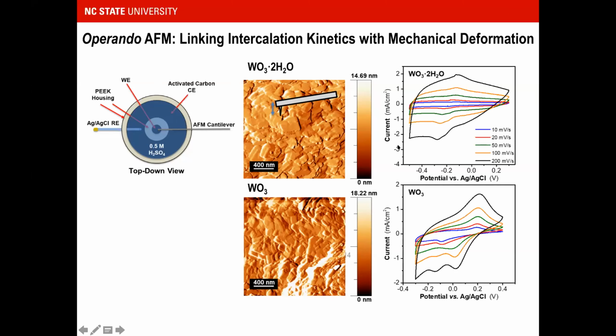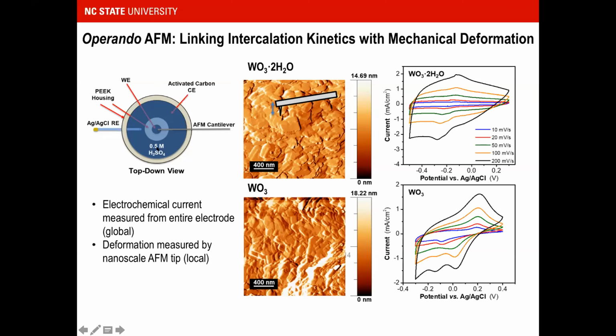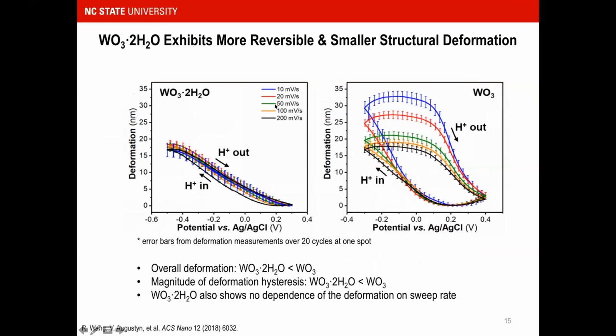And these are the cyclic voltammetry curves from this particular cell. So what we're measuring is the electrochemical current through this electrochemical cell that's coming from everything on the electrode, as well as the very local deformation from the nanoscale tip that's coming from this operando AFM result. And what's really exciting is that we saw when we had the hydrated structure, it had much more reversible and smaller structural deformation. So the deformation magnitude was lower when we had water in the structure versus when we didn't. But also this hysteresis was much smaller, almost non-existent, meaning that the reversibility of proton intercalation, deintercalation was much higher.